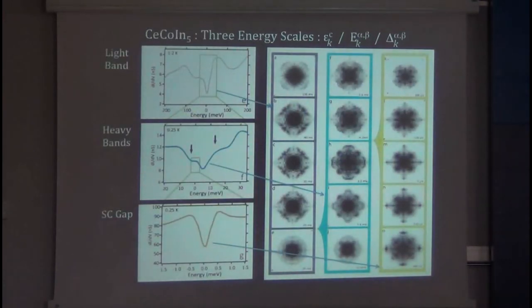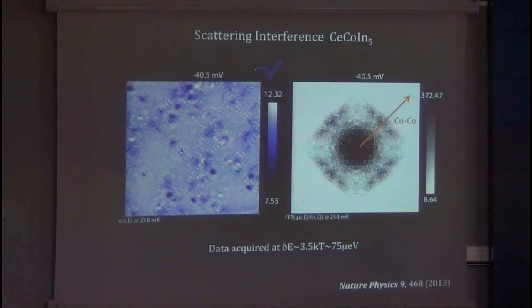And that produces a dynamic range challenge for the STM experimentalists in the audience. Think about this. You have to make a spectroscopic map, a Fourier transform map, hundreds of millivolts wide to get the light band. Then tens of millivolts wide to get the heavy band, and then a few hundred microvolts wide to get the superconducting energy gap. And ideally, you should do it in the same field of view with the same register. So it took a while to get this right. But in the end, we succeeded.